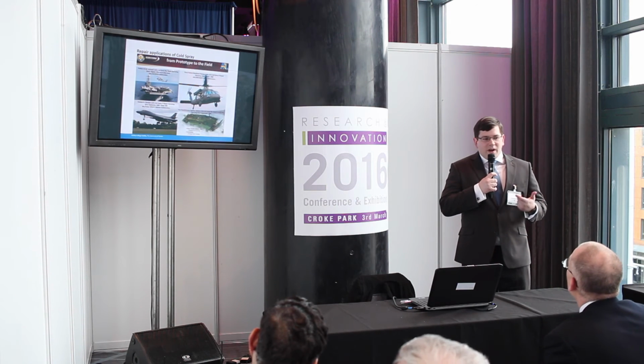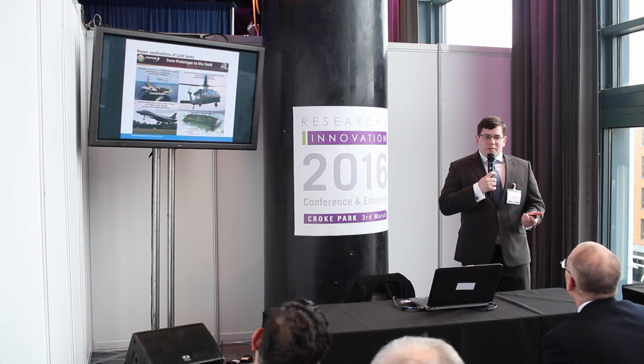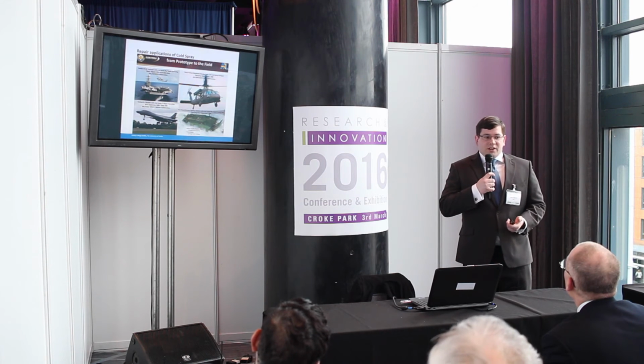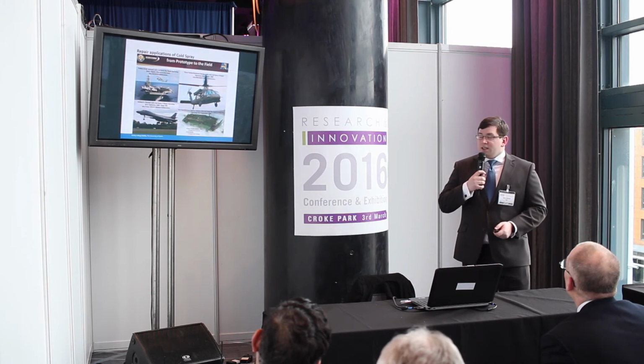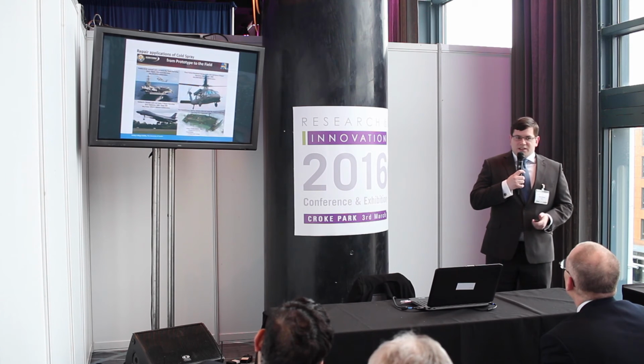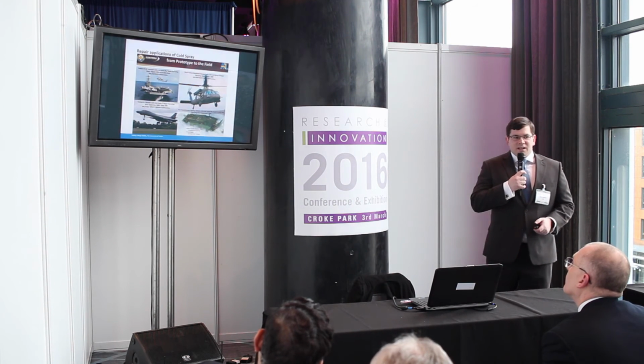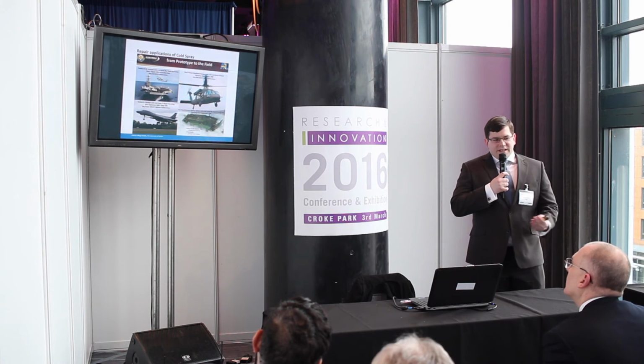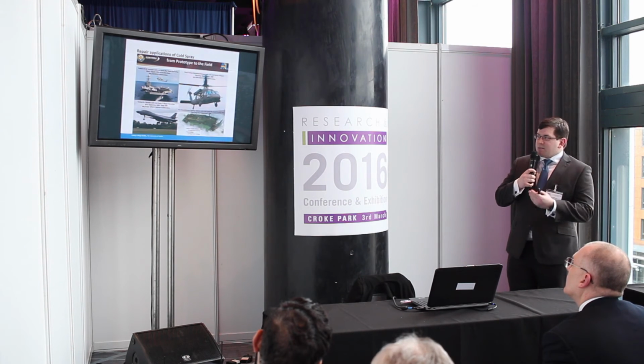If you get wear on the inside, unless you can repair that, you have to throw it away and you have to get another six-figure gearbox housing. It's made of magnesium, so you can't really weld onto it; it doesn't generally end well if you try that. Cold spray aluminium onto it, grind down to get back to the original geometry, and it's back in service.